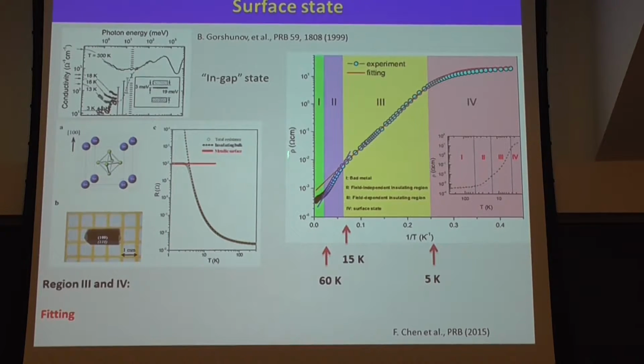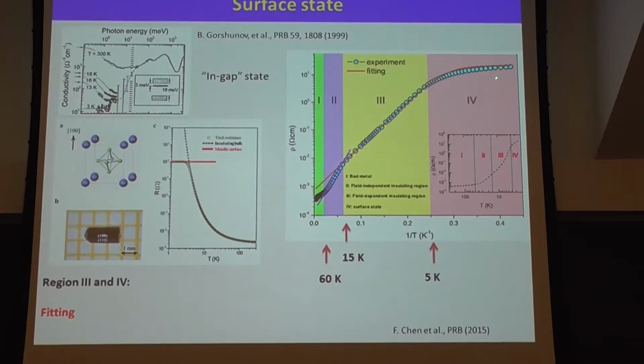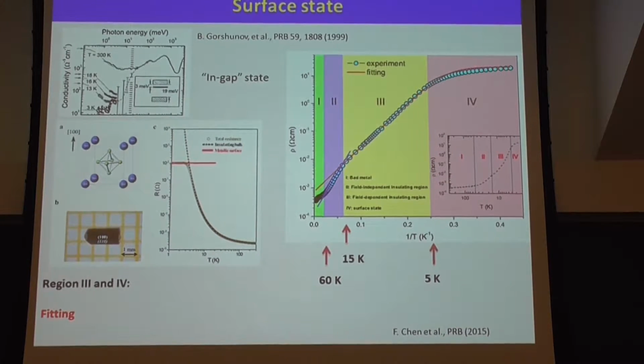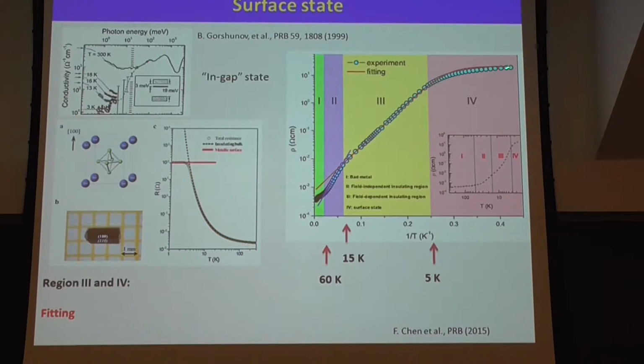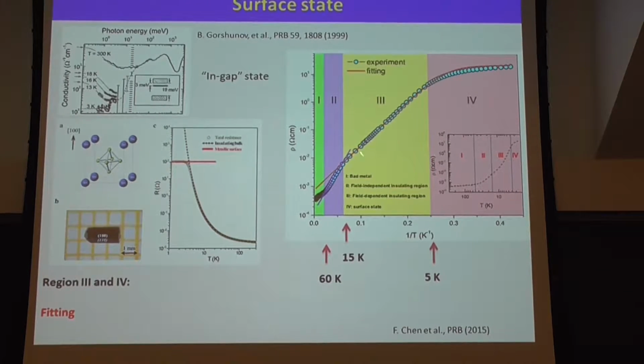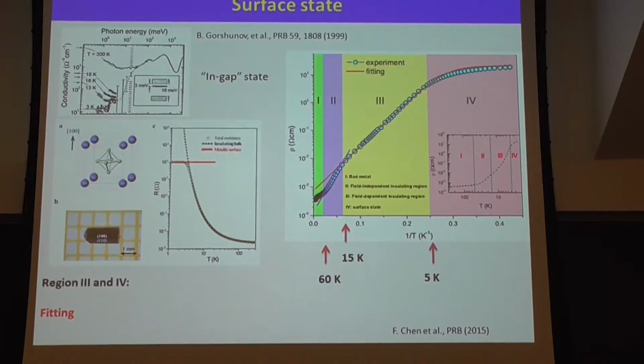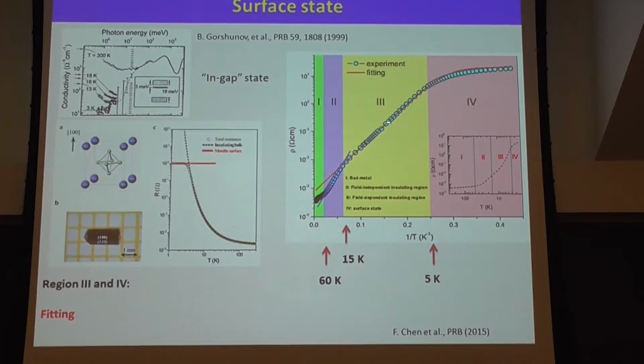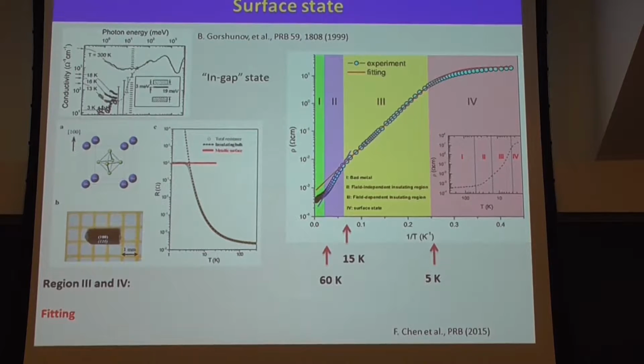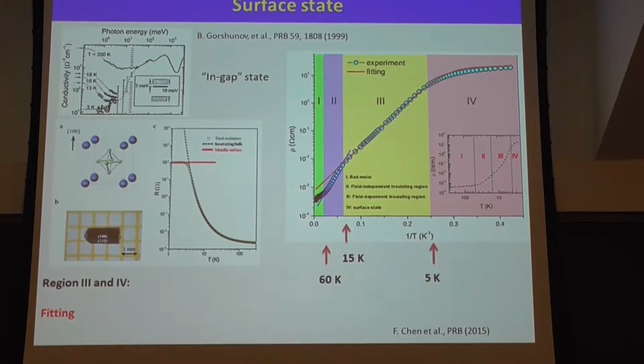The resistivity as a function of temperature shows the Arrhenius behavior, ln ρ versus 1/T. From this resistivity we can derive four regions. As I mentioned, this is the flat region, and this flat region is the surface state. Then here are region 3, region 2 and region 1. Region 1 is right now the bad metal, but the other two are insulating regions. Later I will show you the difference in the insulating behavior of these two regions.